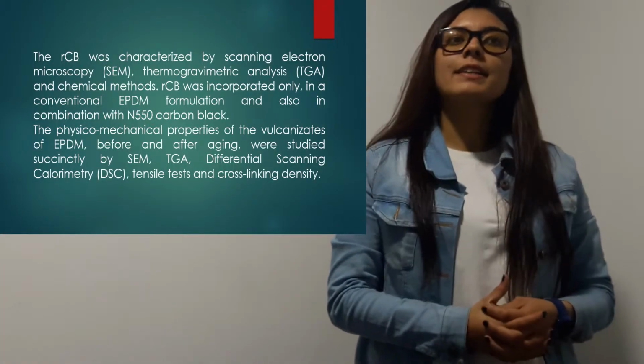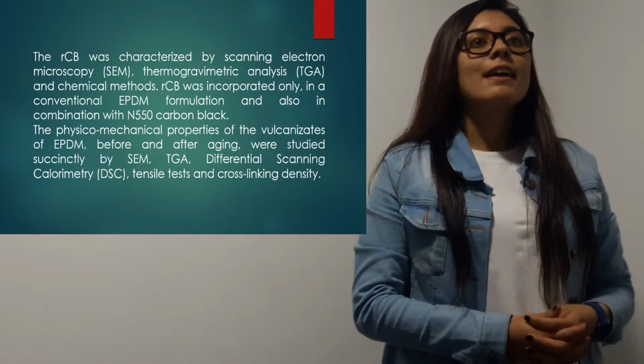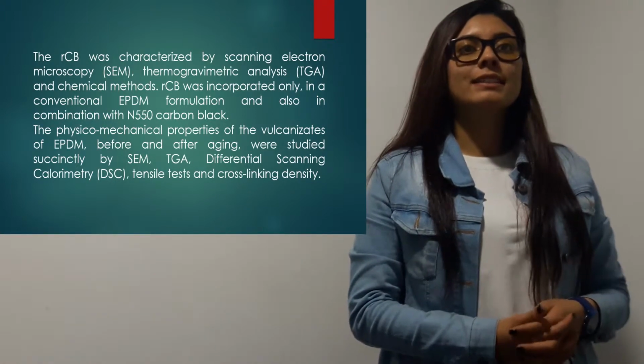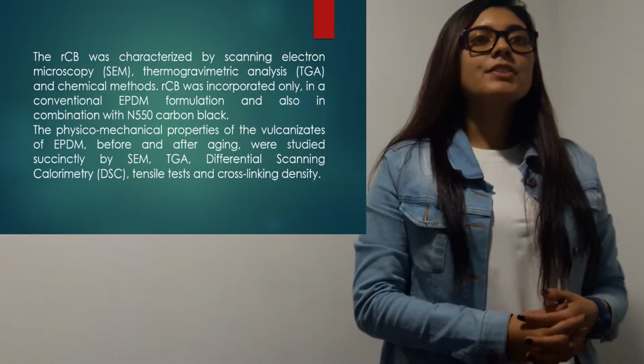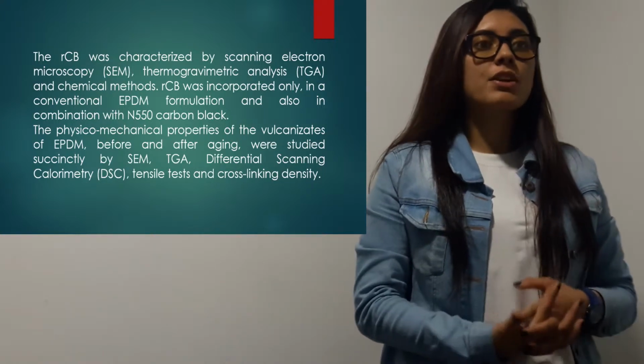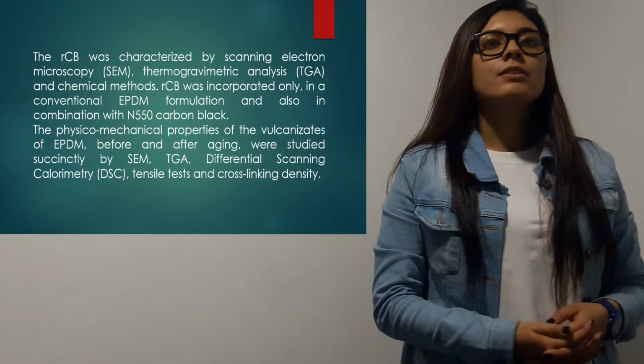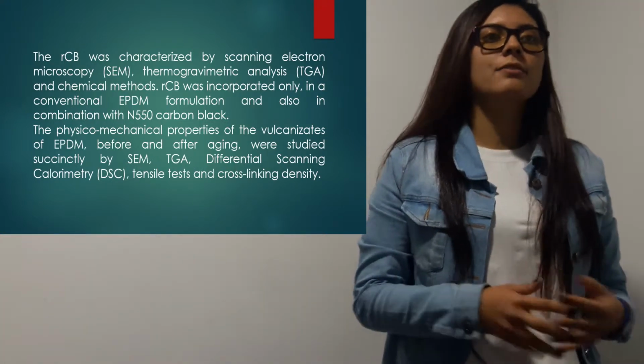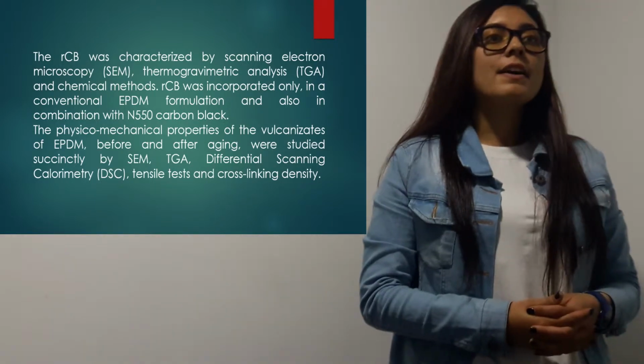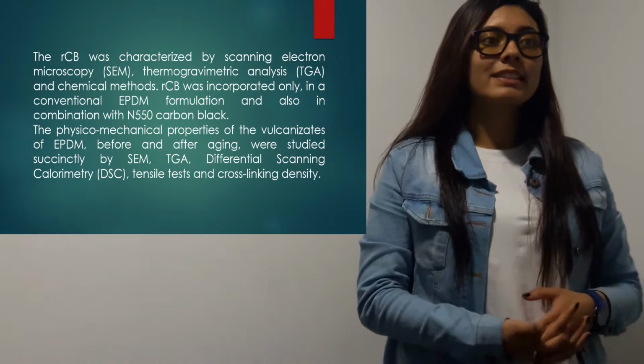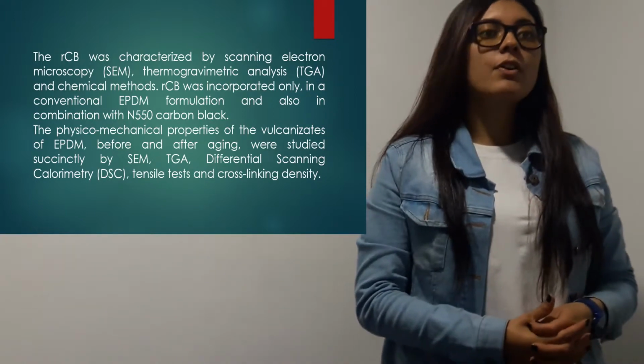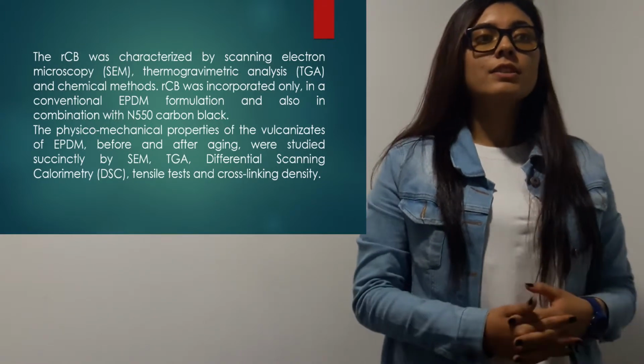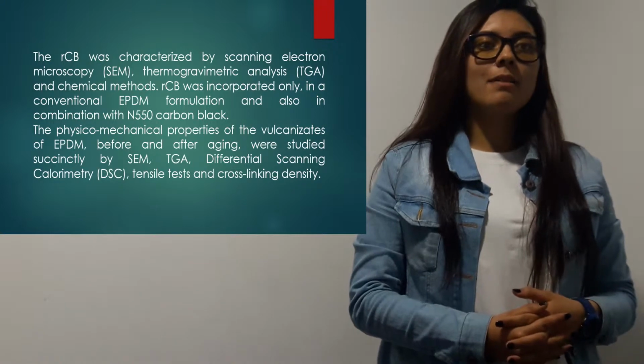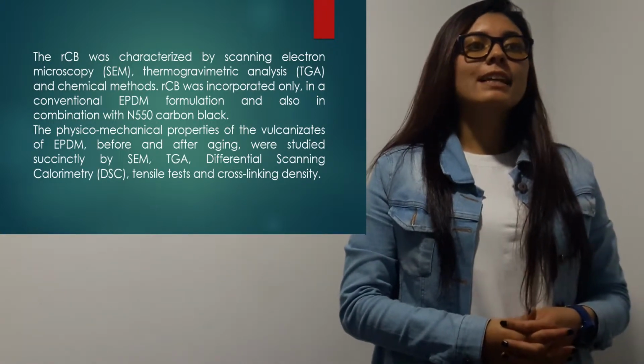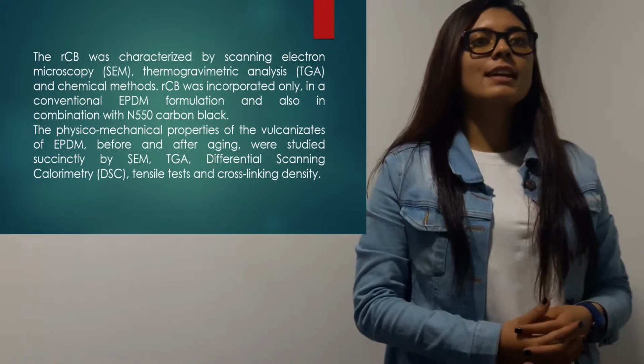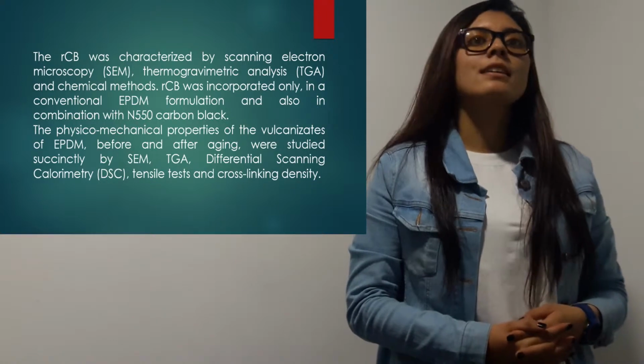The RCB was characterized by scanning electron microscopy, SEM, thermogravimetric analysis (TGA), and chemical methods. RCB was incorporated only in a conventional EPDM formulation and also in combination with N550 carbon black. The physico-mechanical properties of the vulcanizates of EPDM before and after aging were studied successively by SEM, TGA, differential scanning calorimetry, DSC, tensile test, and cross-linking density.